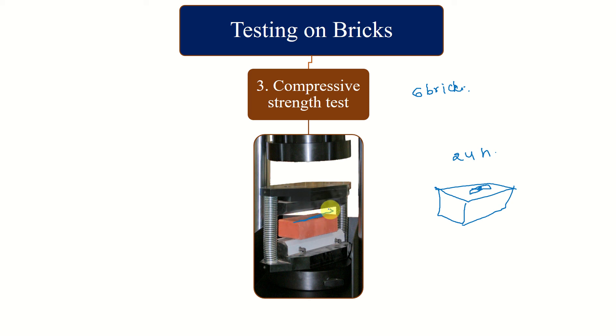Now the specimen is placed in the compression testing machine. Above and below, plywood plates are put in order to get the load distributed uniformly along the length. The maximum load at which failure occurs is noted and the compressive strength is the load at failure divided by area of the section where load is applied. We are taking load in newtons and area in mm square, so compressive strength is in Newton per mm square. As we are taking six bricks, the average of all will be considered as compressive strength for the related brick class.